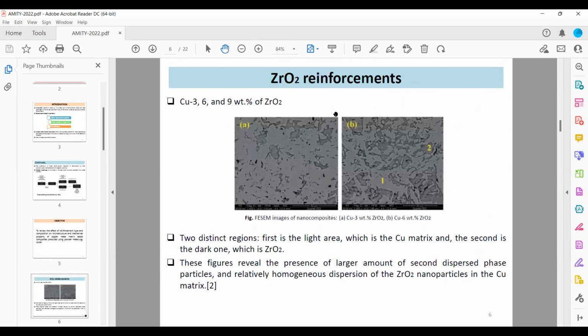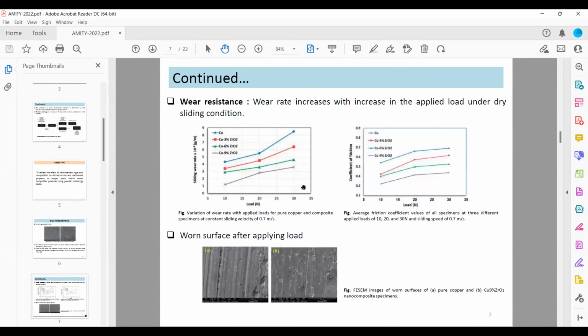Now, first is the ZrO2 reinforcement. When we add zirconium dioxide in the copper matrix, nearly spherical zirconium dioxide particles are homogeneously distributed in the copper matrix. Here the specific electrical resistivity and hardness of the copper zirconium dioxide nanocomposites increase with increasing oxide particle content. The dispersion of ZrO2 nanoparticles yielded good wear resistance for the surface composites when compared with the soft copper matrix. Also, the coefficient of friction indicates small degradation with the dispersion of ZrO2 in the copper matrix.